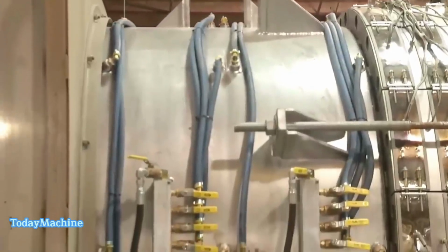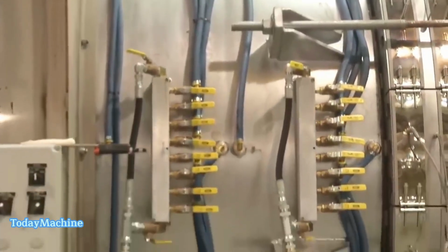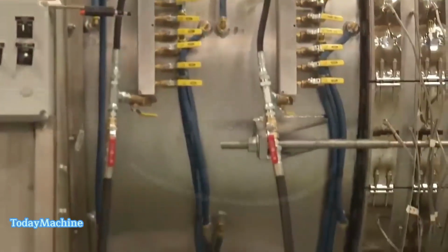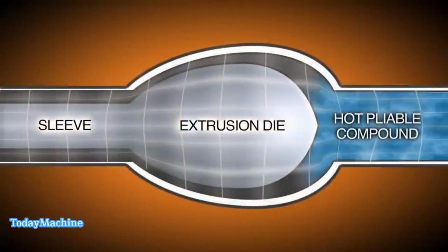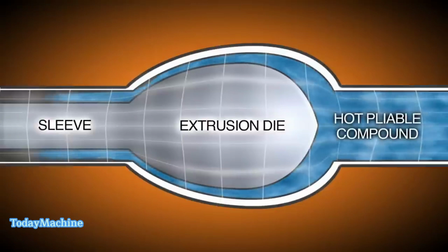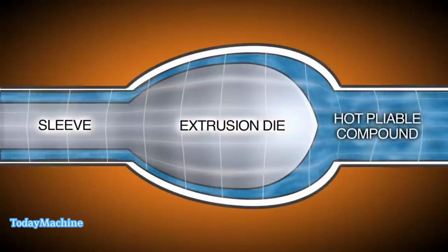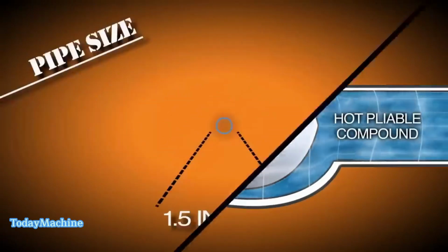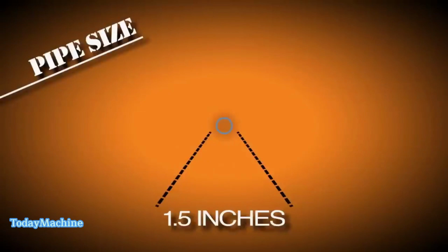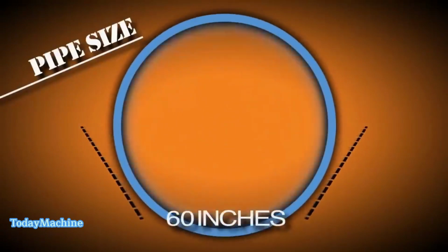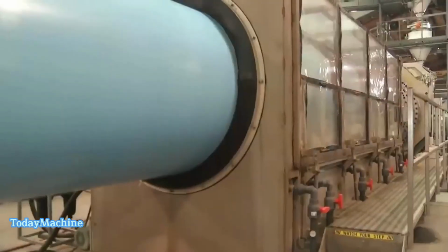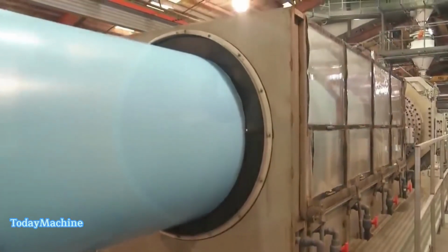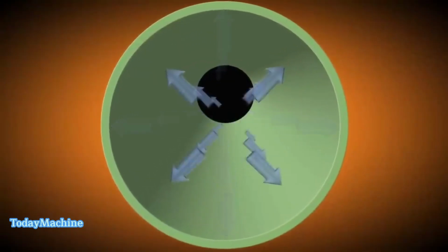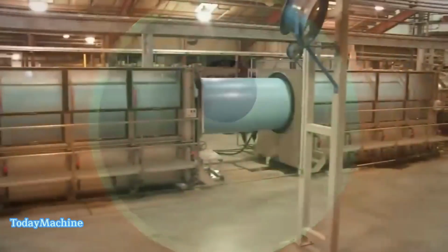After exiting the extrusion die, the hot PVC pipe goes through a crucial cooling process to stabilize its shape and dimensions. The pipe is passed through a series of cooling tanks that are specifically designed to spray chilled water onto the material. The chilled water helps to rapidly cool down the hot PVC pipe, allowing it to solidify and retain its desired shape. The cooling tanks are strategically designed to provide efficient cooling while maintaining the structural integrity of the pipe. These tanks are equipped with spray nozzles that uniformly distribute the chilled water over the surface of the pipe. The water absorbs the heat from the pipe, rapidly lowering its temperature.